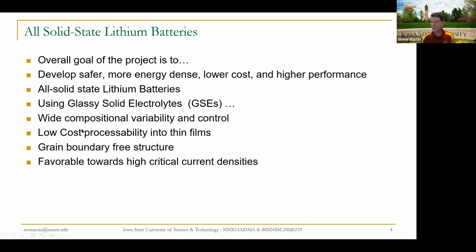And the reason we work with glasses is because glasses are a frozen liquid, and you can take advantage of the wide solubility range in the liquid state, and then you freeze that to the glass. And because you can change the composition over wide ranges, you control properties, and as a result you can adapt the glass to meet all of the many properties you need for a lithium battery. I'll talk about those requirements in a moment.